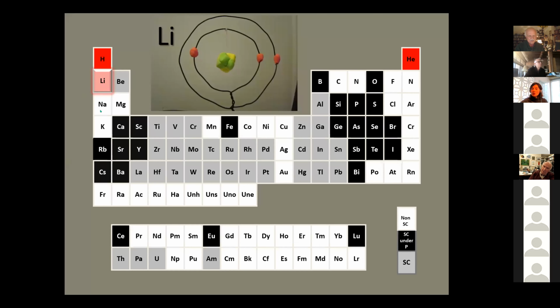That is that sodium and potassium, they have charge density waves. So it could be that at high pressure, we destroy that charge density wave. But at ambient pressure, I don't think the reason they are not superconducting is because of this charge density wave. At higher pressure, they may become superconductors. The thing about sodium is that it remains awfully free electron-like to 1 megabar. So if anything happens, I would guess that it is about 1 megabar.